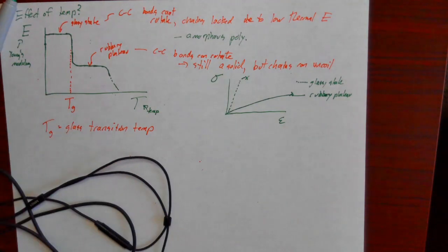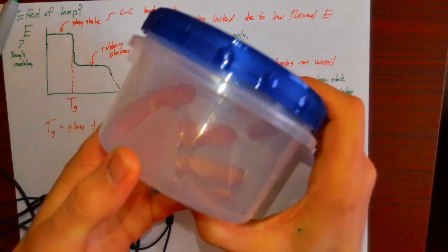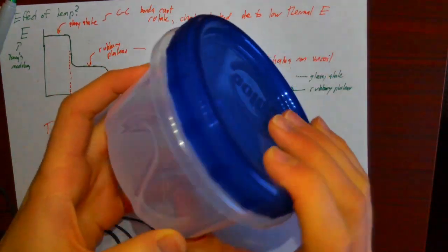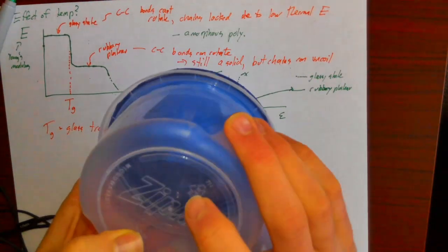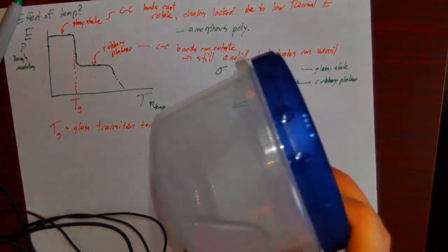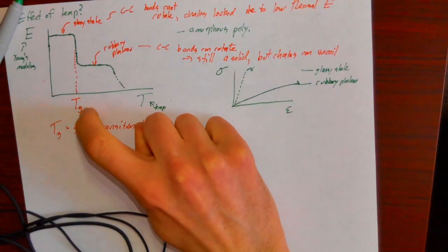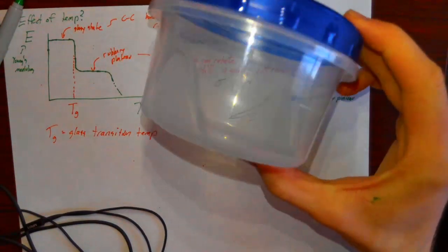So some time ago, there was a disaster in the Lannon household. I had made a bunch of pesto, and I was going to freeze it to enjoy it all throughout the winter. I took a whole bunch of leftover containers made of polypropylene, recycling number 5, and froze my pesto in them. But it turns out that polypropylene's glass transition temperature is pretty close to the temperature of my deep freezer. I took one out of the freezer and dropped it, and the container just shattered.